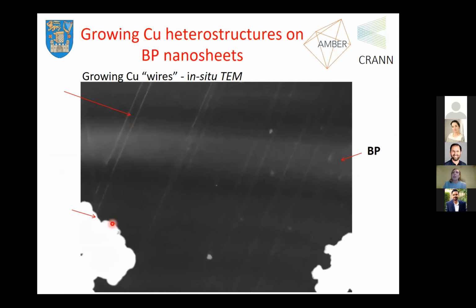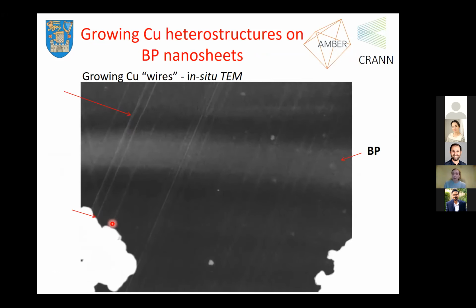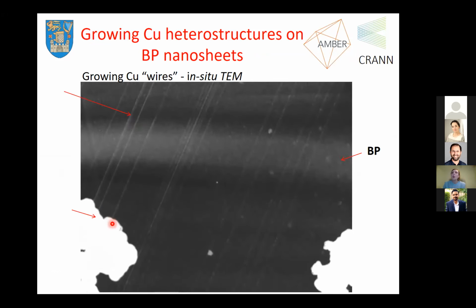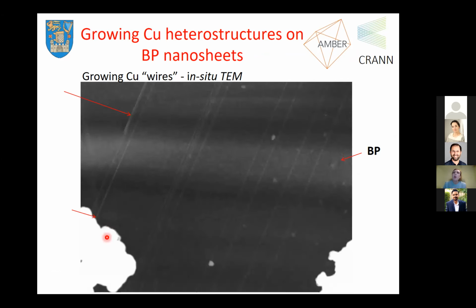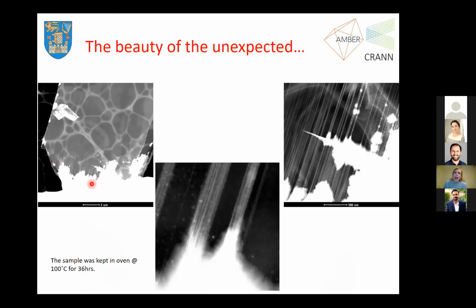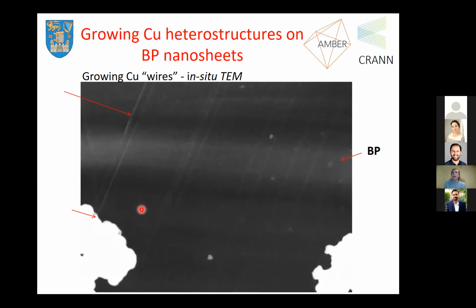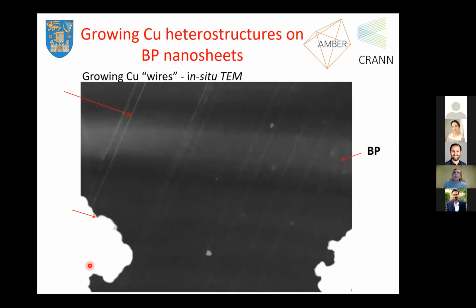Then we decided to repeat the experiment in an in situ TEM setup. So what we did was exfoliate black phosphorus and then sprinkle some metallic copper nanoparticles on it, so as to reproduce these junctions where the black phosphorus was touching the copper grid of the TEM support. And then we increased the temperature up to 80 degrees Celsius. And what we found was very striking. Here I put some arrows.